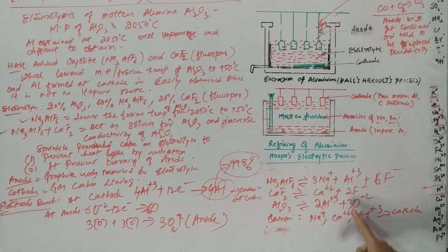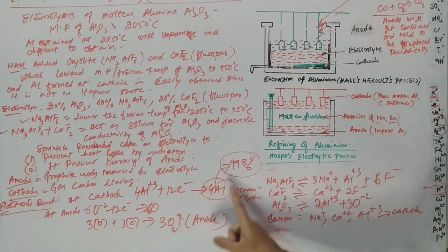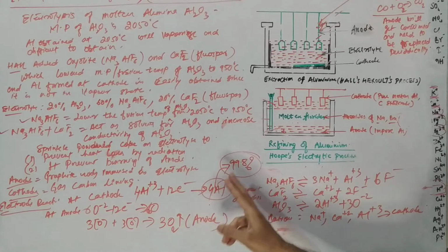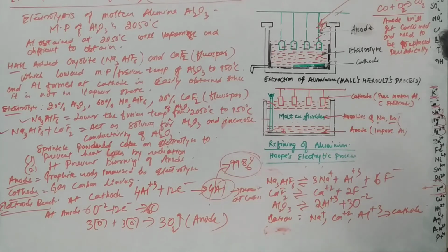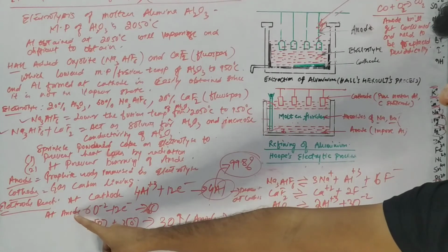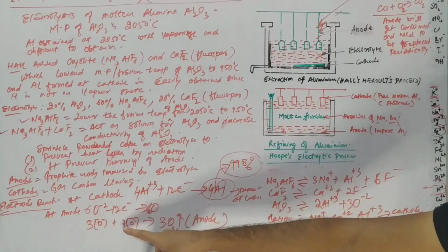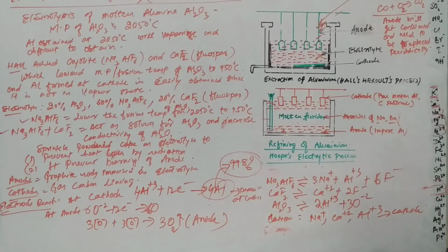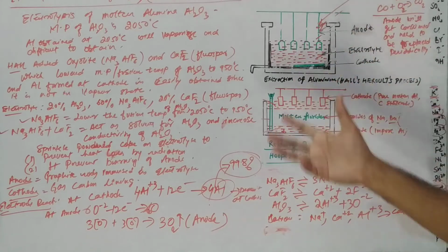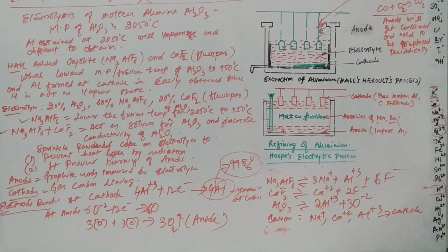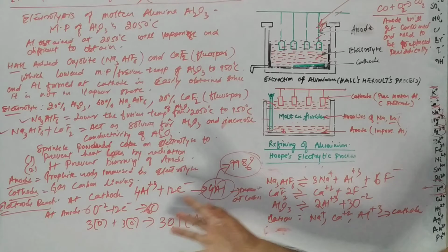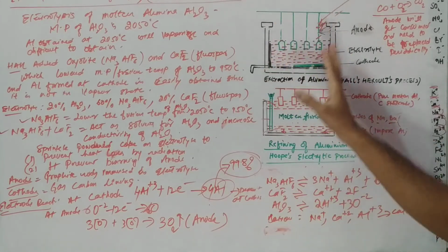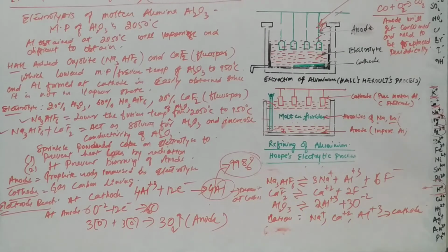So cations would be sodium, calcium, aluminium. All these three will migrate to the cathode, but aluminium, being lower in the electrochemical series, will discharge, forming aluminium, which is deposited at the cathode. This aluminium obtained is 99.8% pure, right? And at the anode, the oxide ions will lose electrons, undergo oxidation, and form oxygen gas. This oxygen gas will react with the graphite rods, which are of carbon, forming carbon monoxide and carbon dioxide. Due to this reaction, the anode will get consumed, or slowly get used up in this electrolytic process, so they need to be replaced from time to time, right?